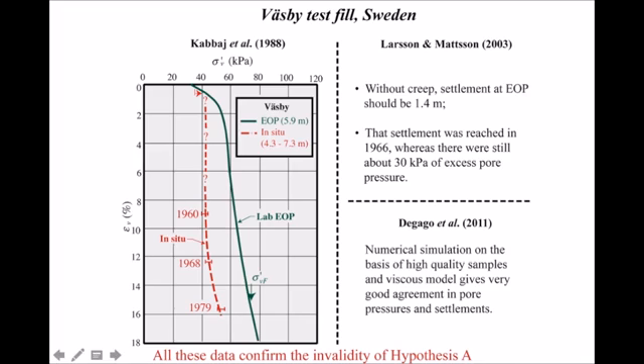Okay, Larsson and Mattsson in 2003 reanalyzed the Väsby case and came with these conclusions. Without creep, settlement at the end of primary should be 1.4 meter. That settlement was reached in 1966, so about here, whereas there were still about 30 kPa of excess pore pressures, which is very close to the 25 we have here, in fact. It's similar. But that indicates that hypothesis A is not correct.